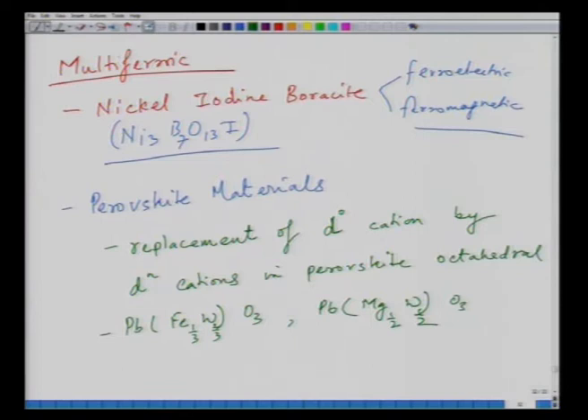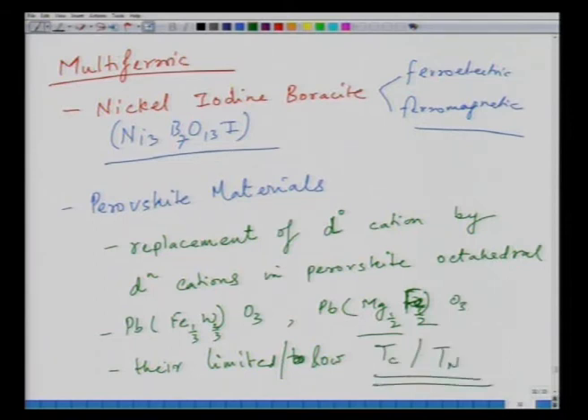And here the ferroelectricity was caused by diamagnetic magnesium and tungsten ions. Sorry, here it would be iron and magnesium, and the magnetic ordering was caused by this iron ion. So this was the basis of discovery of these materials. However, these materials were a little unsuccessful simply because of their limited, or rather I shall say low, Curie temperature or Néel temperatures. So as a result, they did not prove really commercially attractive.